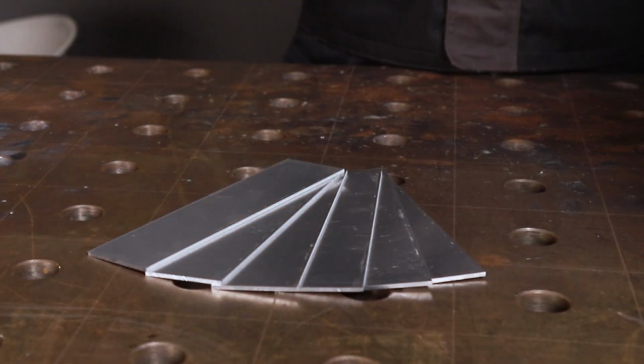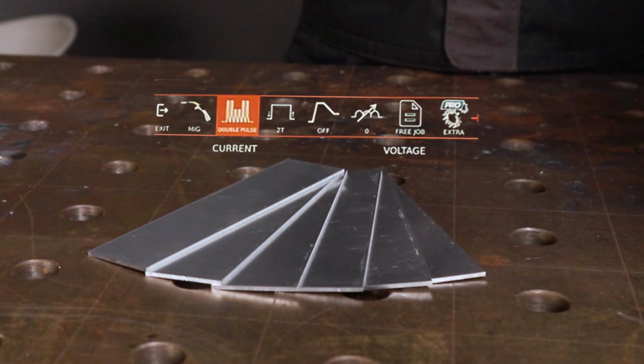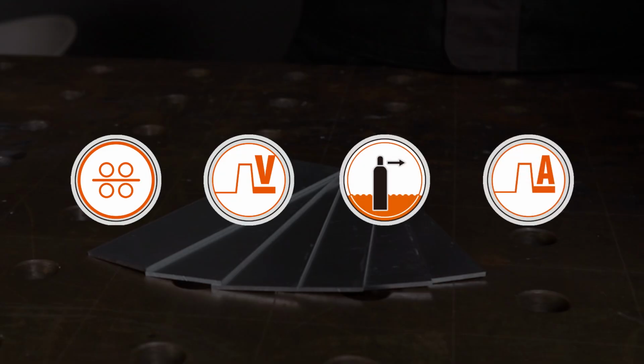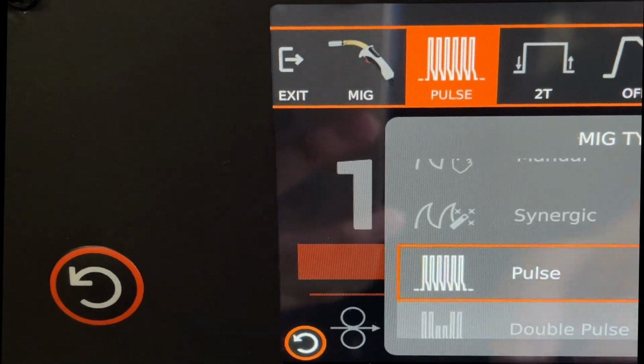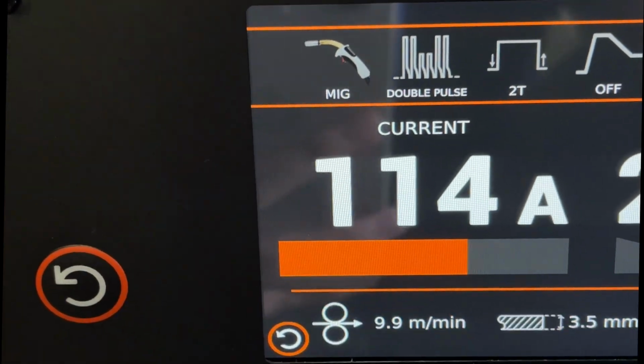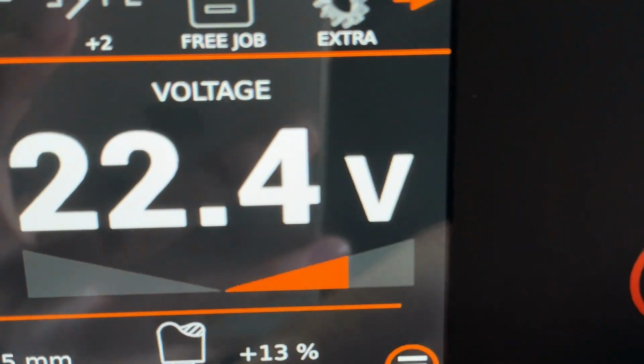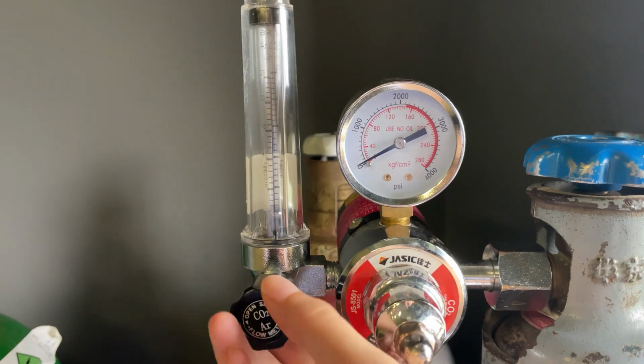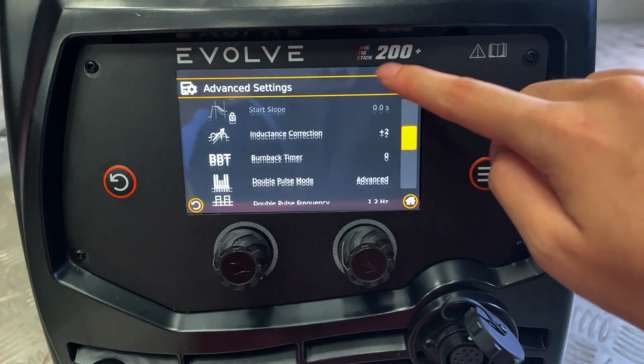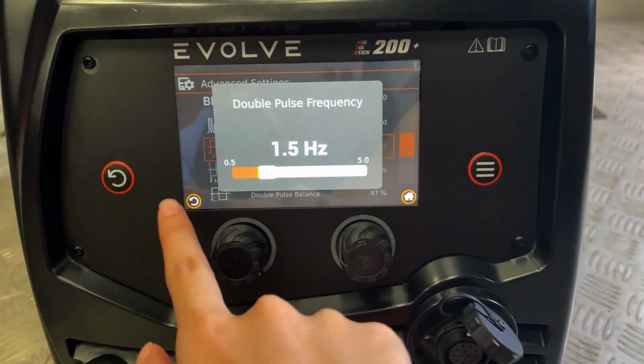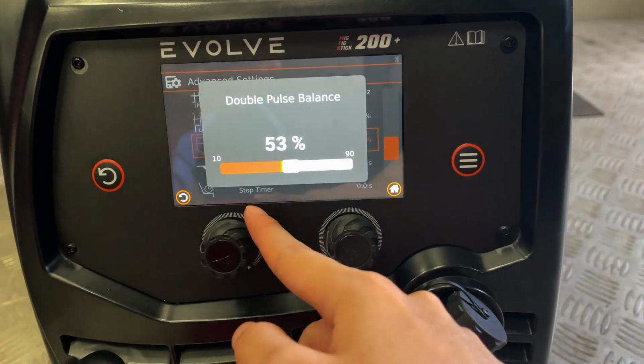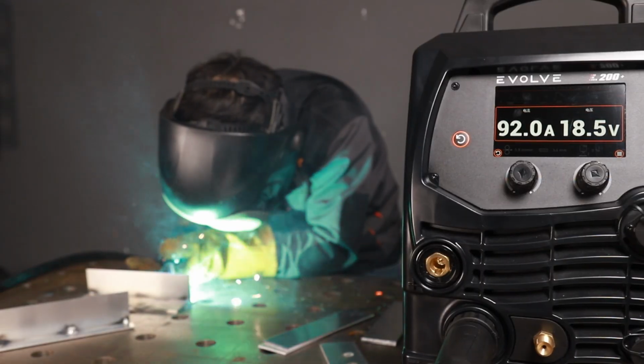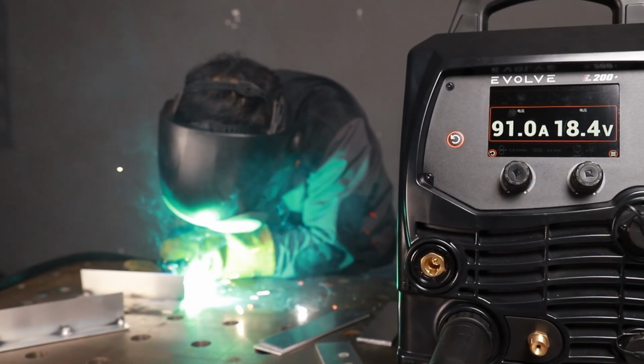Achieving optimal results in welding different aluminum alloys involves adjusting numerous welding parameters such as wire feed speed, voltage, travel speed, heat input, shielding gas flow, arc length, and other factors. For example, when welding 1/8-inch 4043 alloy with double pulse MIG, you might start with around 114 amps and 23.8 volts, use a flow rate of about 20 cubic feet per hour, pure argon, and a 0.035-inch diameter filler rod with a pulse frequency of 1.5 Hz and a 60% duty cycle. Each parameter affects your welding result, and finding the right balance requires detailed knowledge and experience.